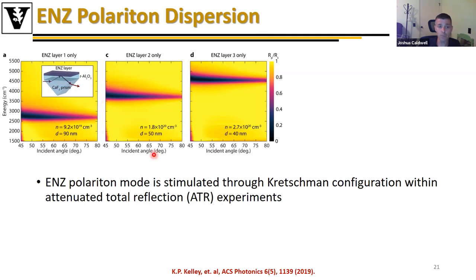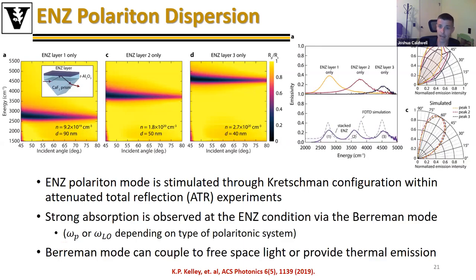These are three different films with different carrier densities, all with thicknesses below 100 nanometers. You can see that the absorptive resonance of the ENZ polariton observed through this Kretschmann configuration becomes spectrally shifted accordingly. Thus, if I heat this up, I get thermal emission resonances where I need them. Each of these layers, compiled into a three-layer structure, gives me individual resonances as if they were individual structures themselves. So they're nominally non-interacting.